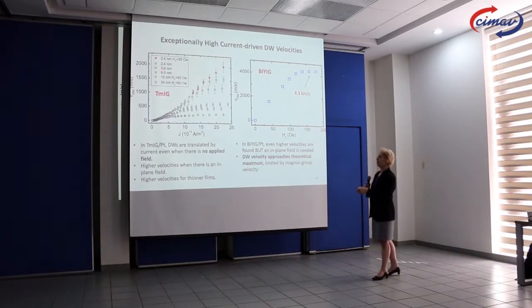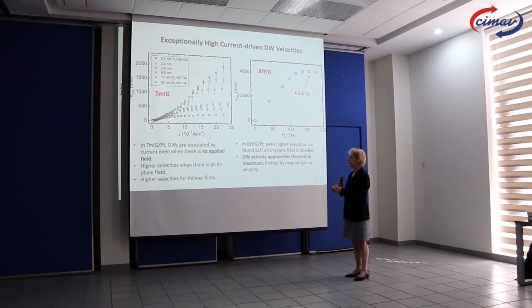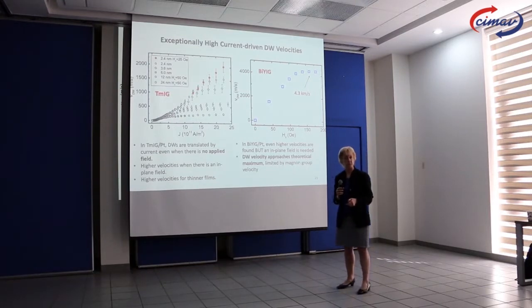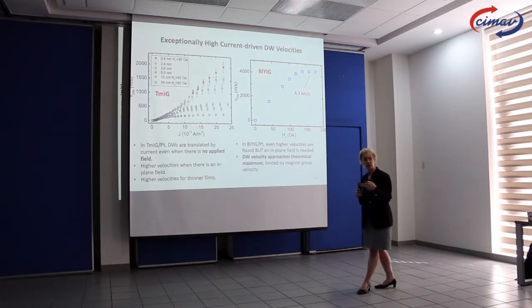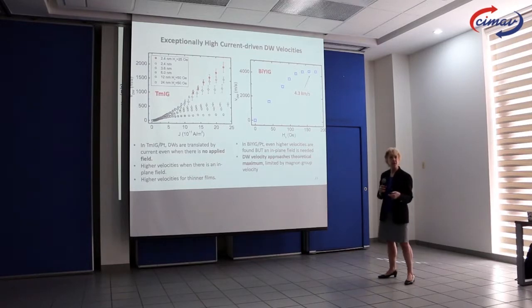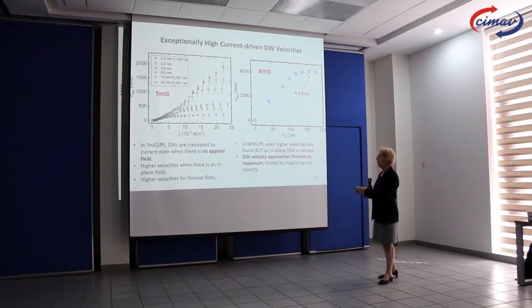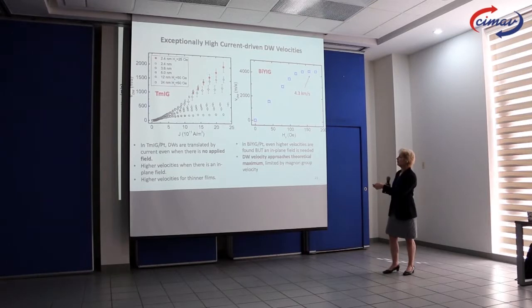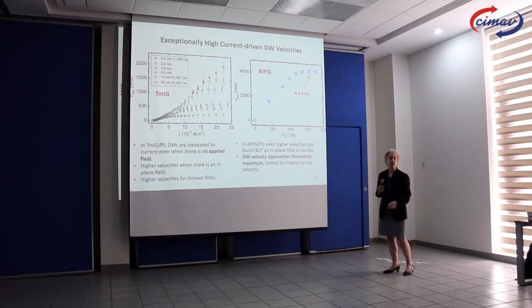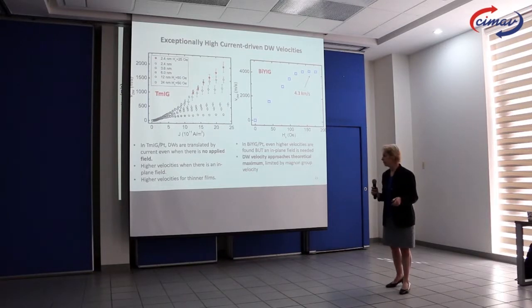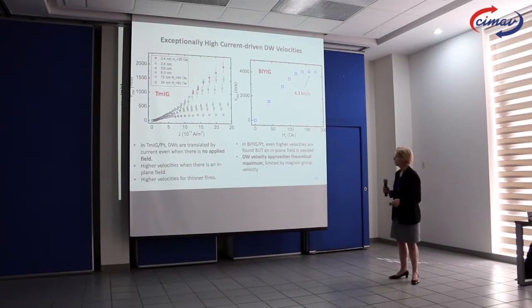The magic thing about the thulium garnet one is that this domain wall velocity, you can get it even when there's no applied field. There is zero field applied in this experiment. It's just the spin current from the platinum that's moving the domain wall in the thulium garnet. However, in the bismuth garnet, if you try that, nothing happens, and that's why we never bothered with it much. But it turns out that if you apply an in-plane field, then it does move, and it moves extremely fast. So what's going on is the next question. Why does it do this?